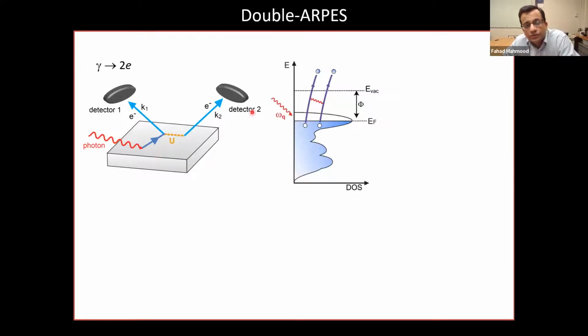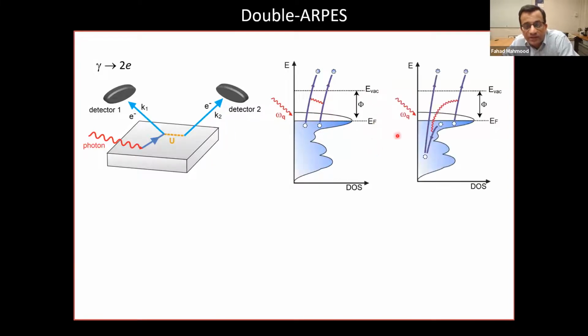Okay, so there are different ways that this can manifest in a system. One way is that you can measure 2 electrons, that you kick out this electron, and then this electron, via an effective interaction with another electron, gets kicked out. Another way is you're measuring core states. So the photon essentially kicks out a core state, this electron relaxes and then interacts with another electron. So this is more like an Auger process. So these are the two ways in which you can get a double photoemission process.